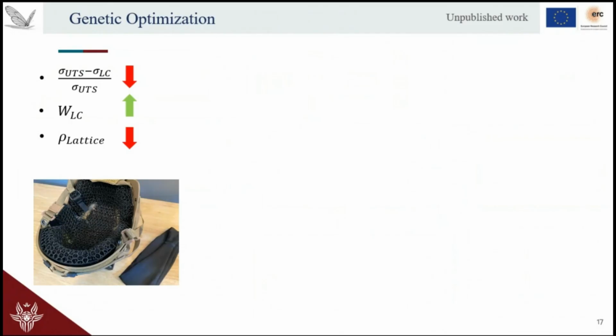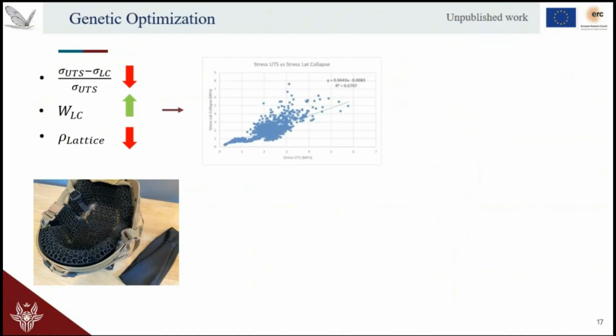So let's explore one very small case study. For example, if we want to optimize a structure for the production of a protection element, for example a helmet, we want to minimize the difference between the ultimate tensile strength and the strength of the lateral collapse, because a huge difference between these two values will cause an increase in experienced G-force, and that could hurt the people using this protection. So we want to minimize this quantity. We also want to maximize the energy absorption, and we want to minimize the density of the lattice to allow a cheaper manufacturing process. So if we let the population evolve, we see those results.